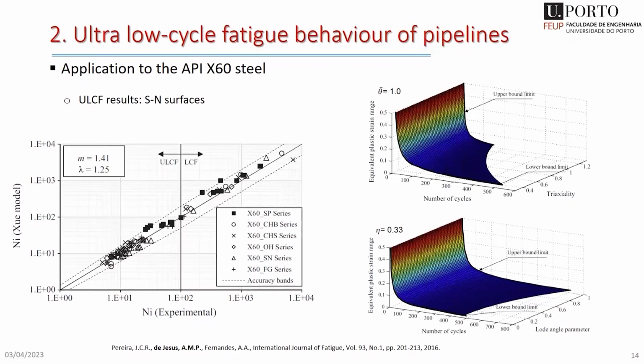Then we need to run cyclic tests, fatigue tests, also covering different stress triaxialities and load angles. And with that, we were able to identify our model. And this approach will lead us to the concept of, we are used to use the SN lines, now we are suggesting the use or the definition of SN surfaces, where you are adding a third dimension to the SN line, which could be this stress state parameter, triaxiality or load angle parameter. Okay, this is the material characterization. As I told you before, this is one of the ingredients that we need for our local approaches.